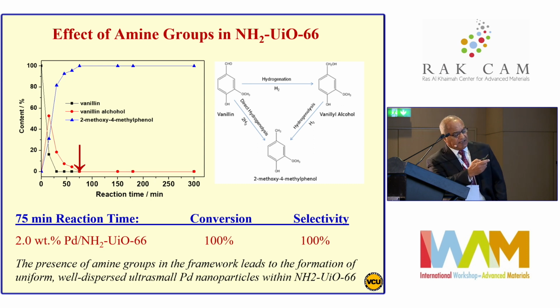So you can see here very different activity, where you see a very rapid decrease in the vanillin, followed by very quick formation of vanillyl alcohol, and then disappearance to form the methoxyphenol as a final product. So we can reach within 75 minutes or so about 100% conversion in this reaction, which is definitely the result that we're looking for. The only problem with this support here is that it requires a relatively high concentration to achieve this result. So we'd like to go below 2% weight of the palladium in this support, but with 2% we can reach 100% conversion, and this is again attributed to the presence of amine in the UiO66.